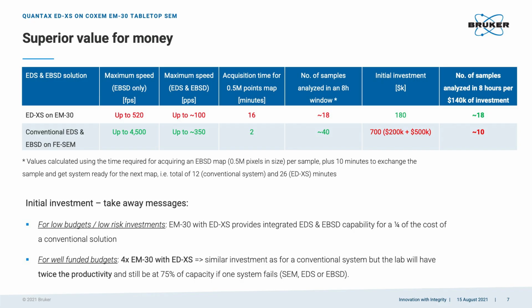Then if you consider doing EDS and EBSD simultaneously, then the EDS technique will slow down dramatically the speed at which you can map, because you may want to have a good number of counts in every spectrum acquired in every point of the map. So then the maximum speeds would be around 100 points per second for the ED-XS, and around 350 points per second for a conventional EDS-EBSD system.